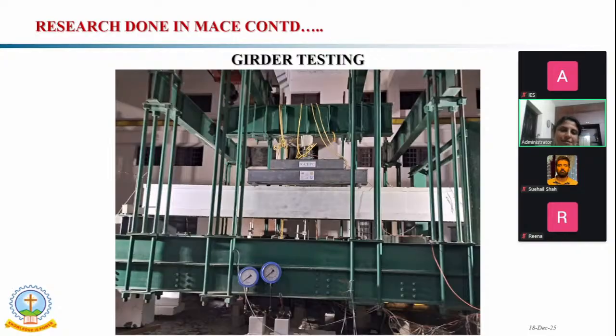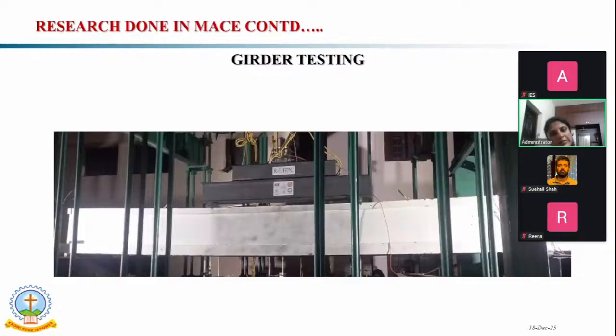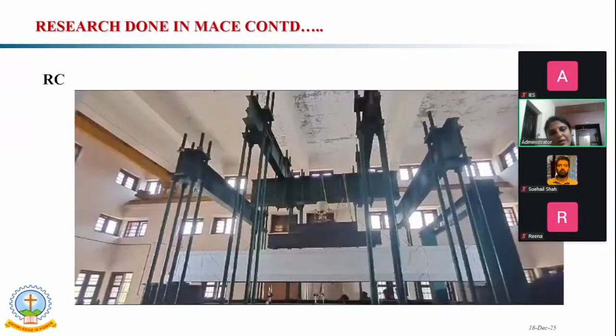But when we considered the UHPC with the rebars, we didn't get accurate results, because when we loaded the UHPC steel bar girder, the loading pressure pump blasted. Only a little bit of crack happened in the case of the UHPC with the steel bar girder, so it didn't fail in that testing. I tested all four.